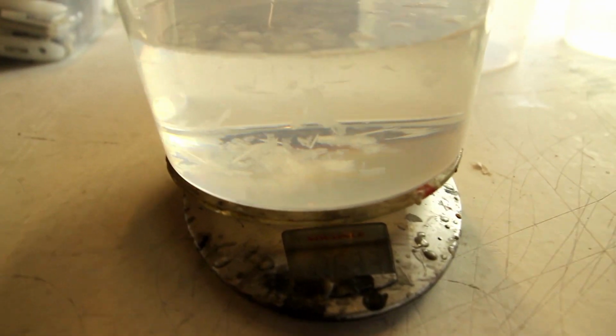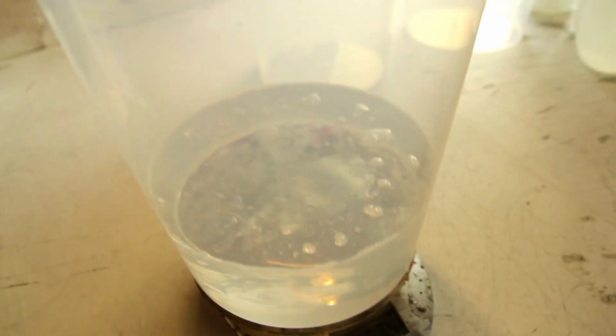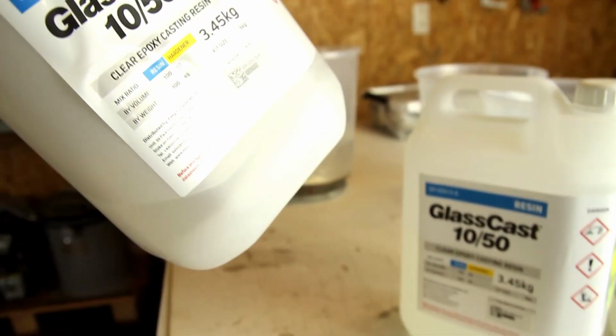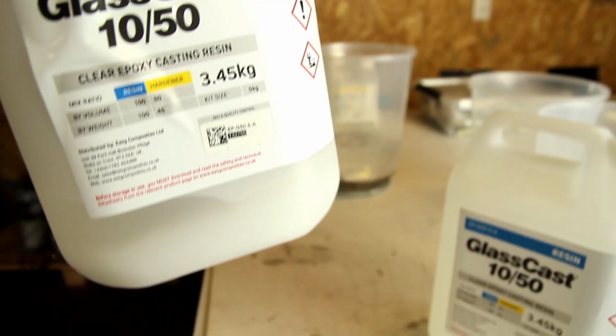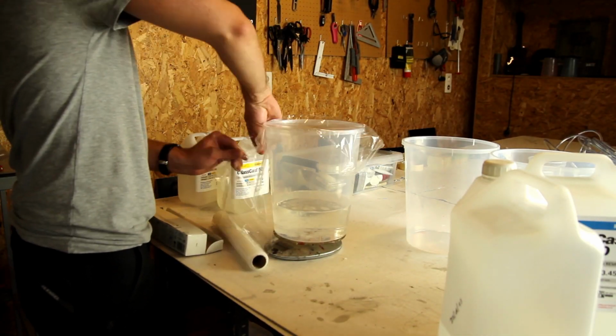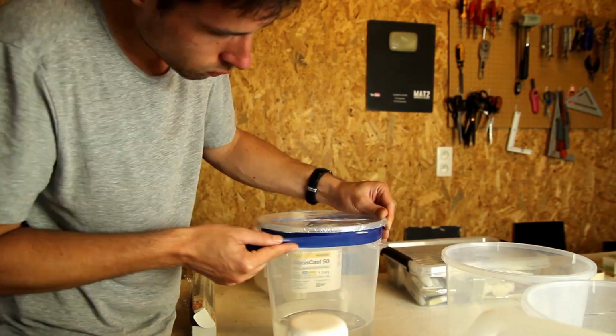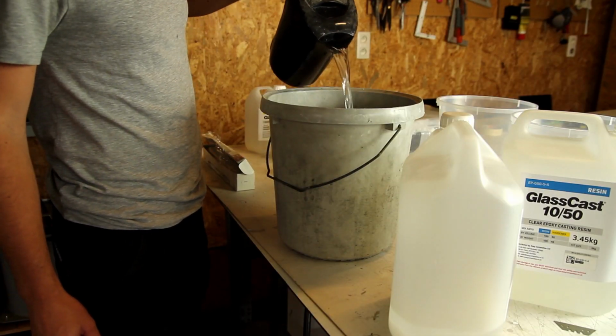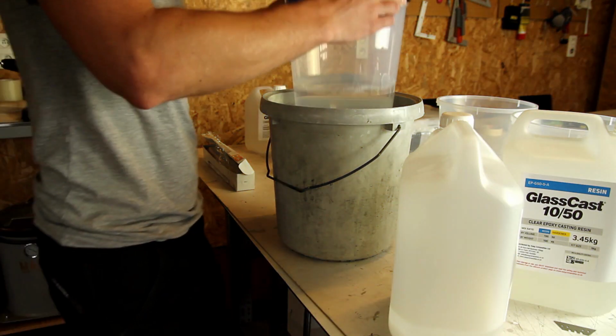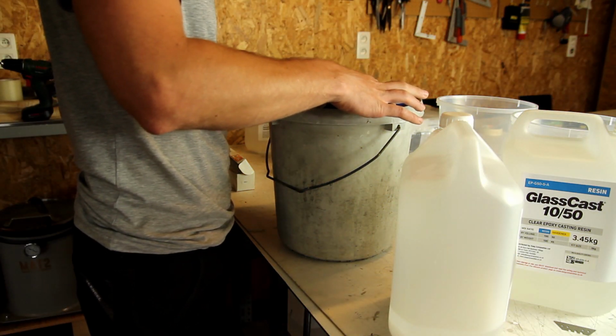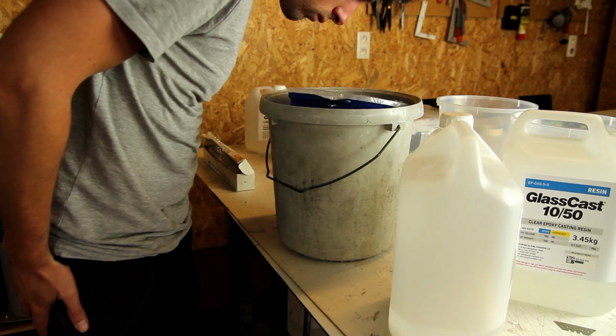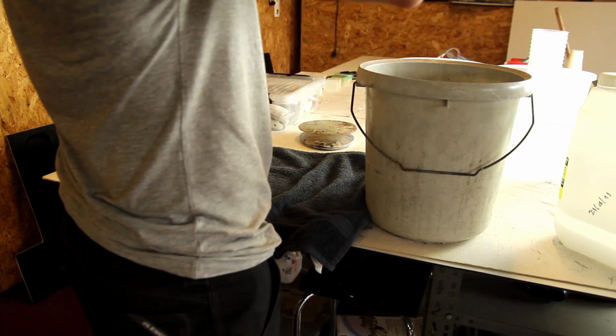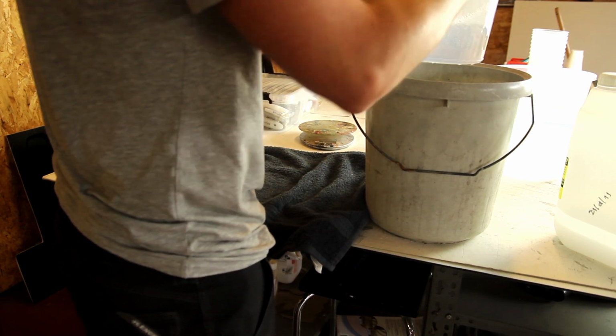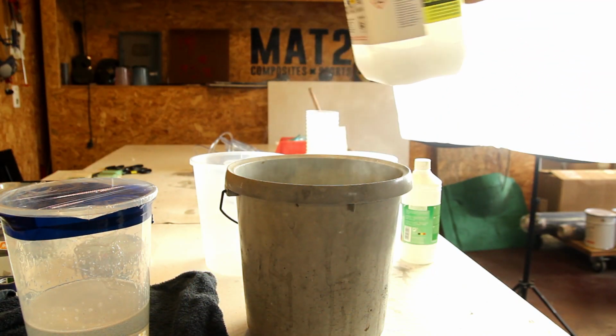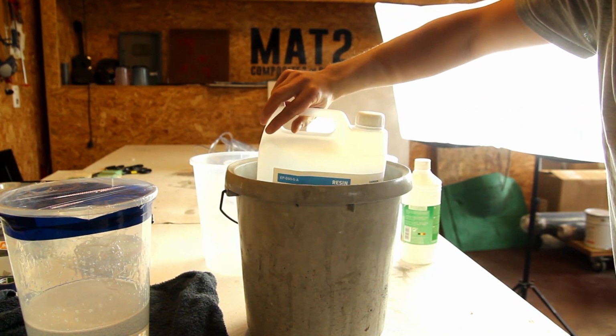Here, pretty important: what you're seeing are some crystals in the epoxy resin. So before you mix, make sure that your epoxy is in the best condition possible. Easy Composites or Glass Cast will put a yellow sticker on it, telling you to keep consistent temperatures in the workshop where you store them. What I'm doing here is reversing the crystallization of the epoxy by adding some heat. This is called au bain-marie in French. You heat it in hot water, and that way you're pretty sure that the entire mass of epoxy resin will heat at the same rate, and that removes the crystals.